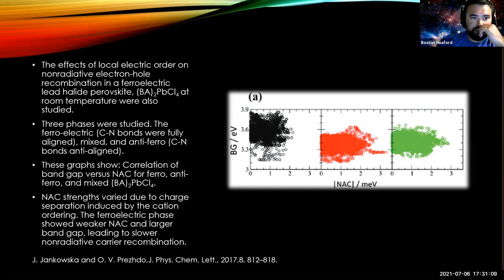And the effects of the local electric order on non-radiative electron hole recombination in a ferroelectric lead halide perovskite were also studied. Three phases were studied, the ferroelectric, the mixed, and the antiferro, where the CN bonds were fully aligned, mixed and anti-aligned. And these graphs show the correlation of the band gap versus the nonadiabatic coupling for the different systems. And the nonadiabatic coupling strengths vary due to the charge separation induced by the cation ordering. And the ferroelectric phase showed a weaker nonadiabatic coupling and a larger band gap, which again led to slower carrier recombination.